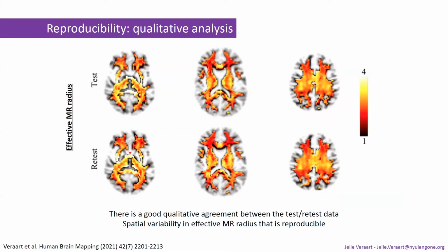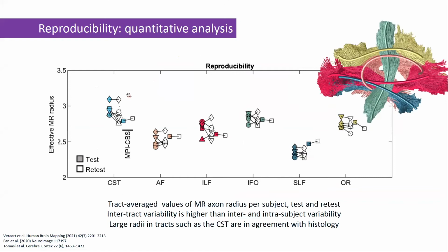I just show the effective MR radius for the test and the retest data. Just a qualitative assessment first. What we do notice is a very good agreement. We see spatial variability that seems to be reproducible. And that made us optimistic that we actually have a useful biomarker here. But we had to be more quantitative.